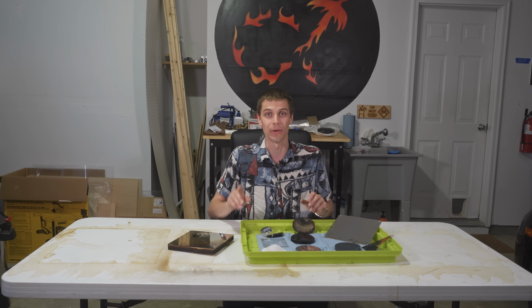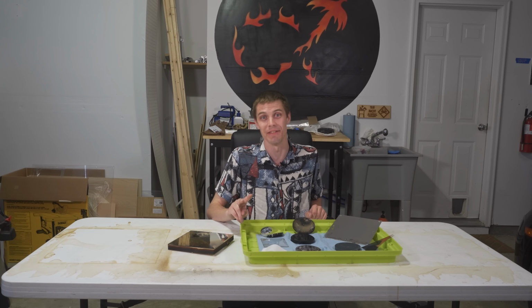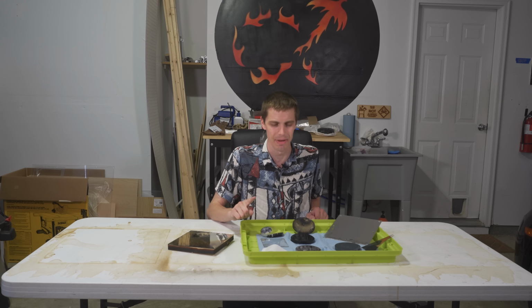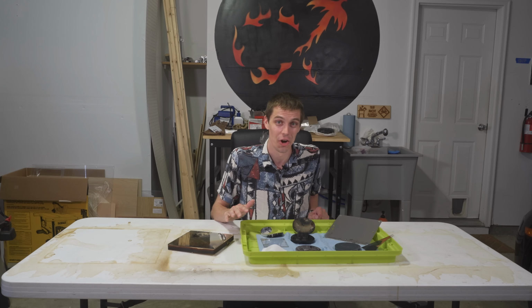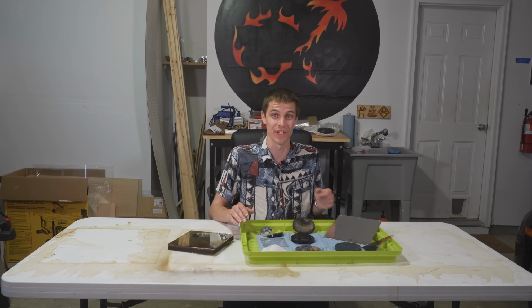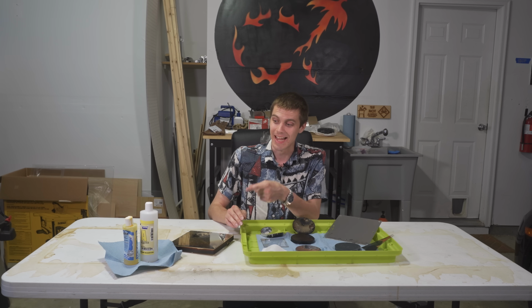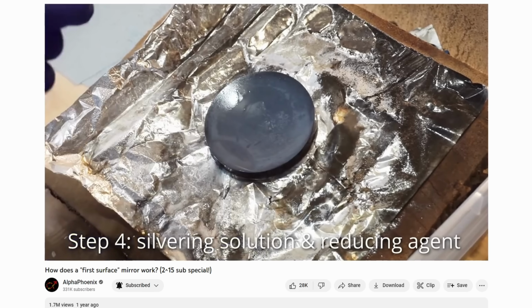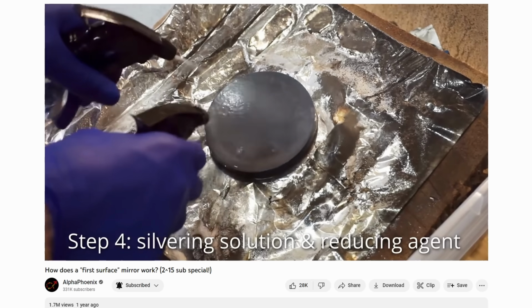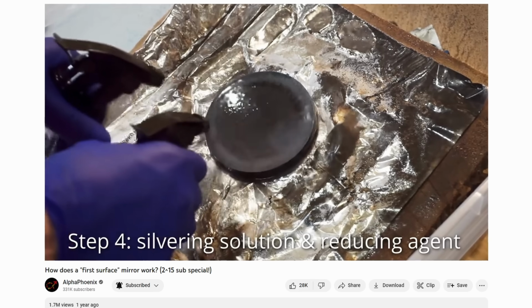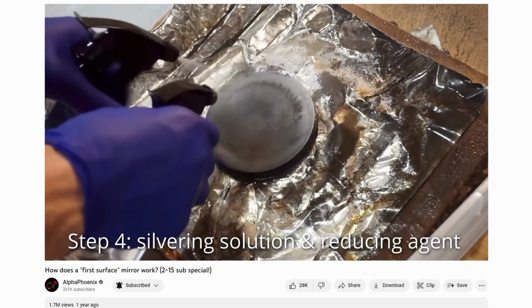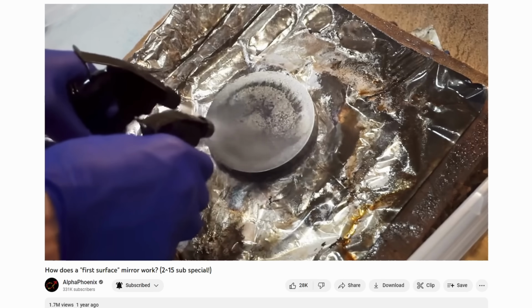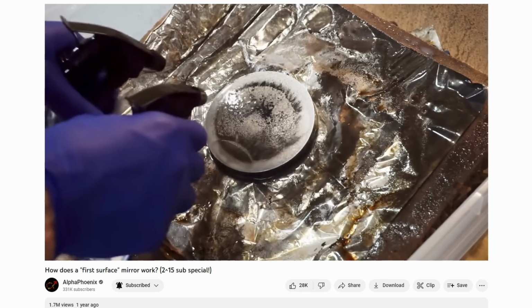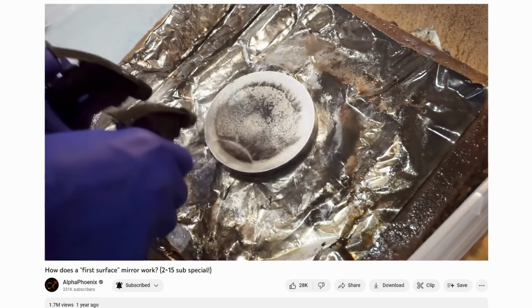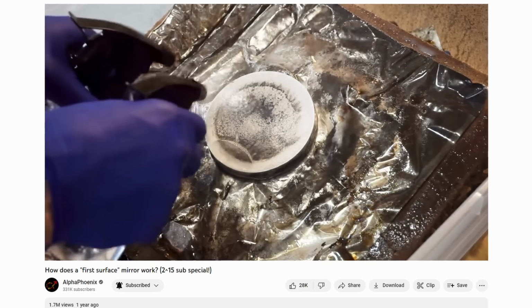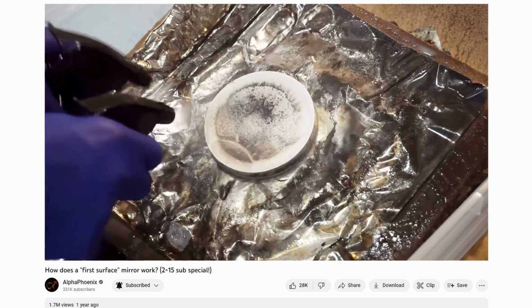The whole patina thing was the second most common comment that I received, but the first most common comment that I received by far was to ditch the two-part epoxy and use UV cure. During that first attempt, I really struggled with finding a mixture of resin that would cure properly and not react with the silvering solution. If the solution reacted with residue on the surface of the plastic that somehow wasn't fully cured, it would still make silver, but it wouldn't be smooth. So despite being metallic, it wouldn't actually be a mirror.